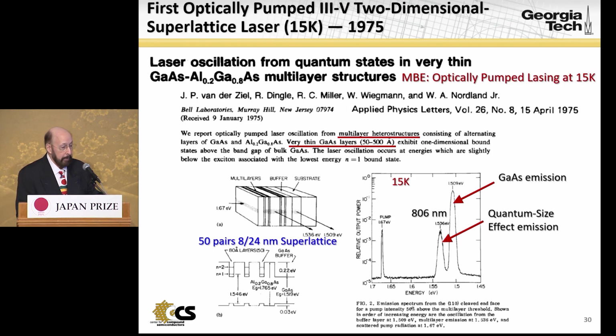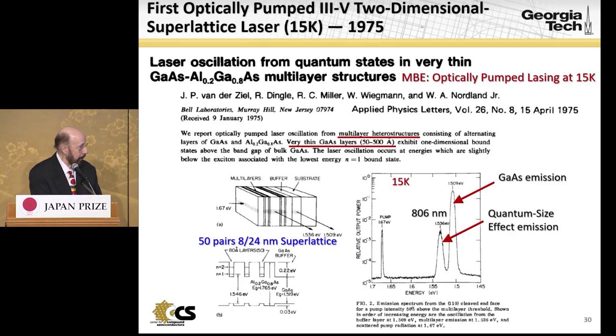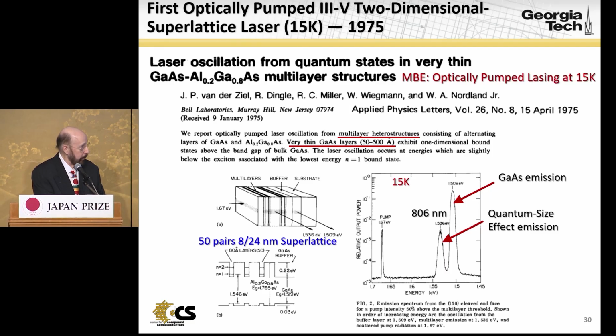The first optically pumped III-V two-dimensional superlattice laser was demonstrated in 1975, operated at only 15 Kelvin, liquid helium temperature. It was composed of molecular beam epitaxy-grown superlattices, which were 50 pairs of 8 nanometer gallium arsenide layers and 24 nanometer aluminum gallium arsenide layers. And this thing was put in a cryostat and optically pumped with a parametric oscillator, really heavy-duty, high-power laser source, and people reported stimulated emission at this 806 nanometers, which was ascribed to quantum size effects because of the quantum mechanics of confining electrons in narrow wells. This peak is a gallium arsenide peak associated with the substrate, they claimed.